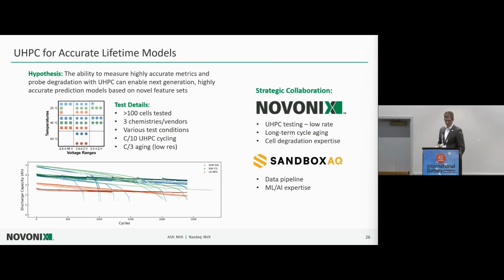We had those 3 types of cells, and then we also played with the SOC ranges. So using the whole SOC range, 2.5 to 4.2 volts, cutting out some of the high nickel cathode upper capacity, so stopping at 4.06 volts, and then also not utilizing all of the silicon capacity and going only from 3.3 volts to 4.2 volts. So we're really turning some of these things on and off, tuning them so that the cells aren't going to fail necessarily the same way every time. This makes it really hard to build a generalizable model just using traditional cycling data, just looking at, say, the first 100 cycles of these data.